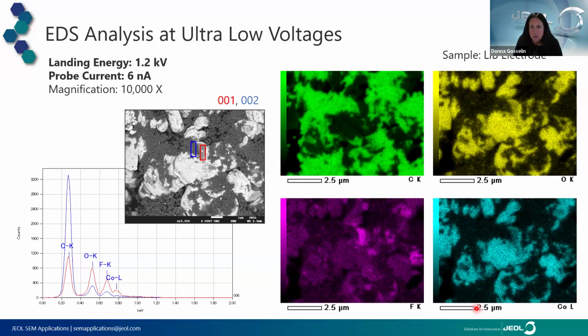So if you look at this map data, you can see that the lighter gray areas are more rich in fluorine. The lower left here, you can see the fluorine X-ray intensity map. And the darker gray areas are more rich in carbon.